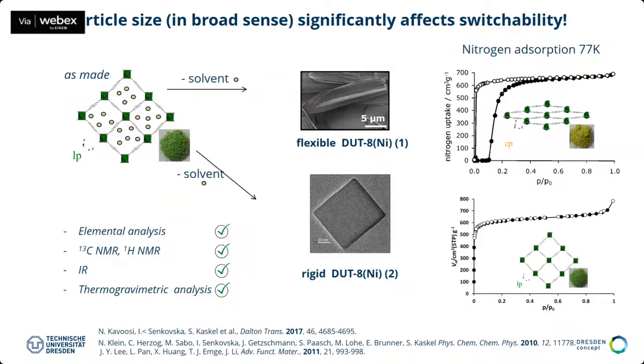Now, one very strange phenomenon for these responsive metal organic frameworks is the importance of size effects. We all know that when we go to the nano regime, everything is different. And this can become very complicated in this class of materials. And what we found, and there's also, of course, other work by Susumu Kitagawa on different systems, but a very important finding is if you make your material, the DUT-8 nickel, for example, as nanoparticle, then the responsivity is completely lost. So there's no hysteresis anymore. The material is open all the time. It does not close anymore. And we call this a type 1 isotherm here for nitrogen adsorption. Only if you have large crystals which are flexible, then you see the flexibility and the hysteresis in the isotherm.